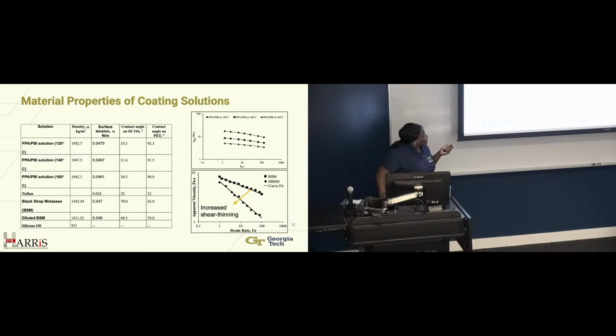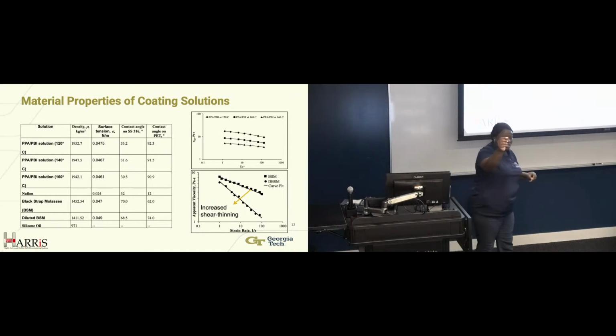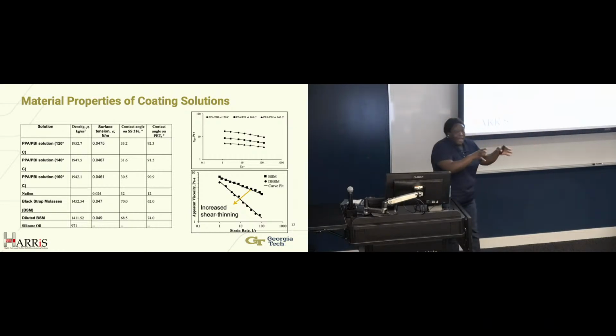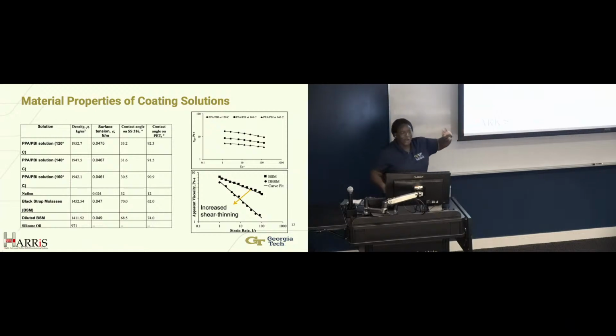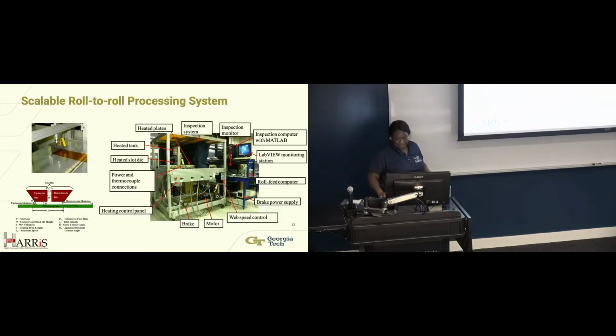For whenever we're processing these materials, the things that are important for us is truly understanding the surface tension, contact angle, and the rheology. Because this is a shearing process, the viscosity will change over time if the materials are non-Newtonian. But we hope that in some of the regions, we can find some Newtonian space. And if we can, then that's the shear rate that we try to aim for, just so we can prevent changes in the rheology, which means we're not in control of the process as much because it's flowing faster or slower relative to the shear inside.